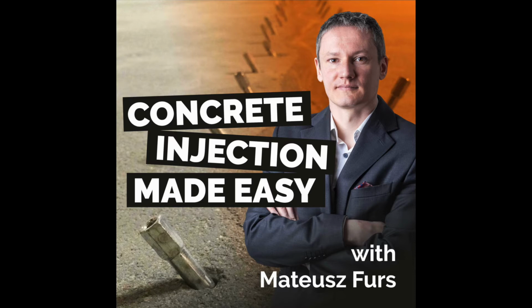Yeah, I know this, and quite often people tell this, because that's true. First, if you consider a pure acrylic, in dry condition you will lose the water you bring from the beginning when you inject, and you will reduce the volume. Okay, so that's on pure acrylic. Then, as I told in the first question, you can formulate or modify the acrylic. When you formulate, you can reduce this drying and also the swelling rates. For instance, some acrylics can swell like 100%. Standard ones swell like 30%, but we can decrease this to 10% and even lower. And then it depends on the job you have to achieve.